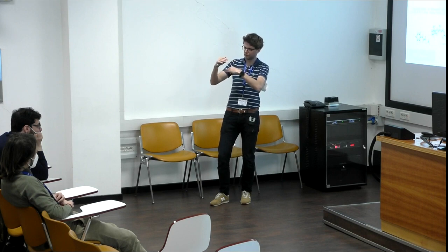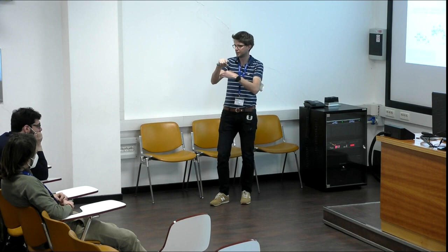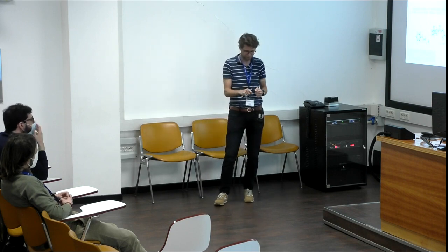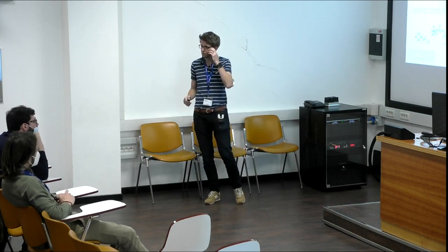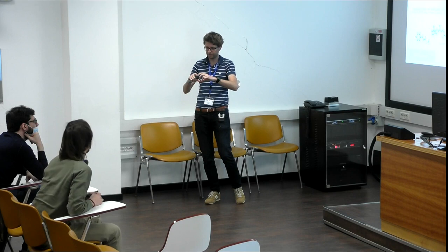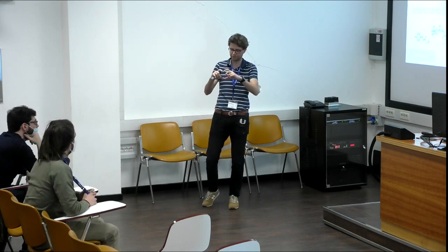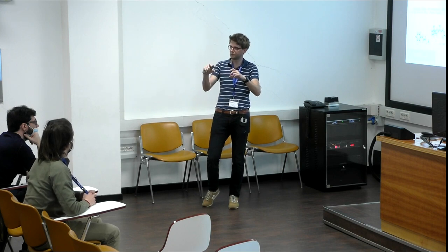You need a kernel which is exactly the difference between the spin-up and spin-down exchange-correlation potential, and this is what you get with TD-DFT. And with BSE, you pretty much get the same. You have the spin splitting, which is determined at the GW level by W, and then you have the W interaction, and this closes the gap.